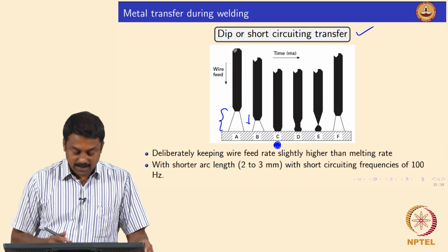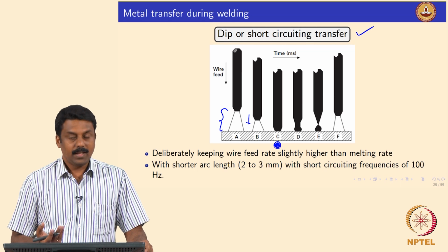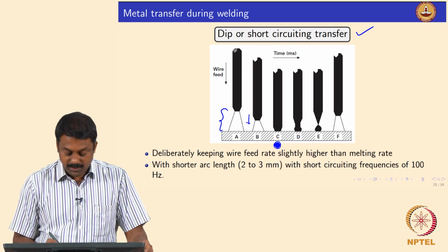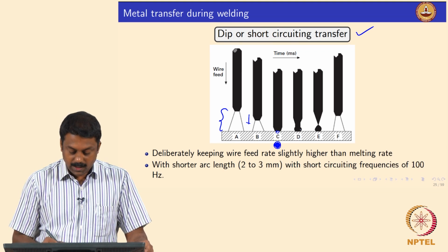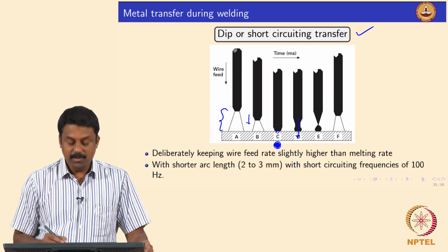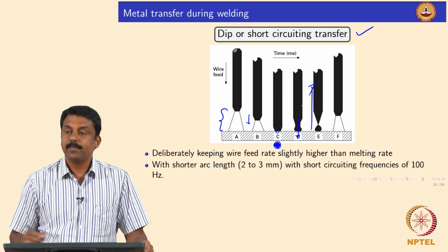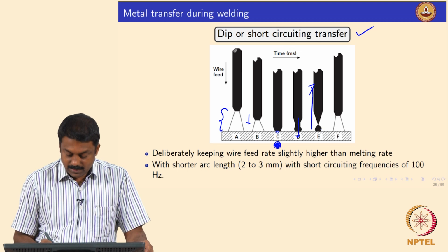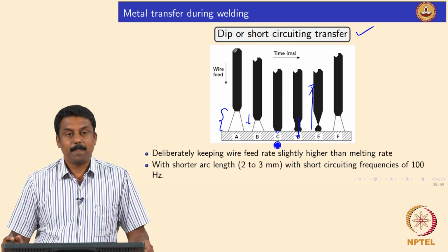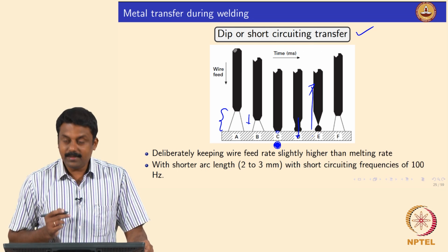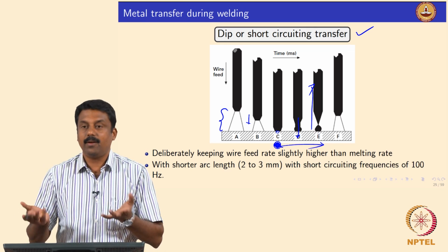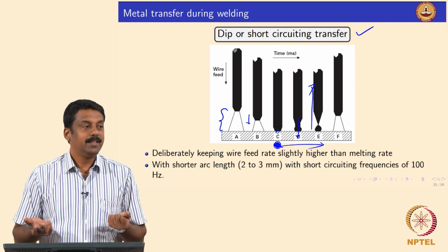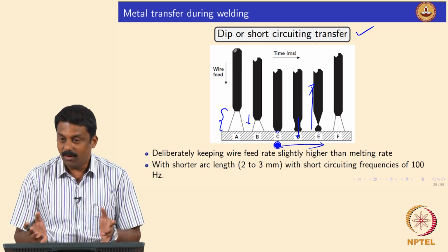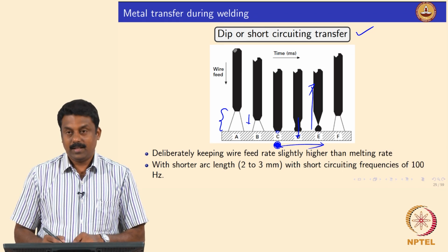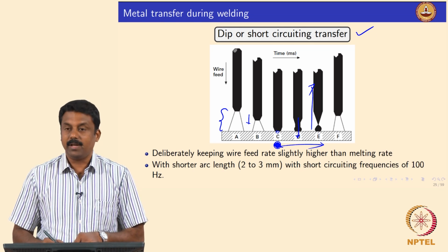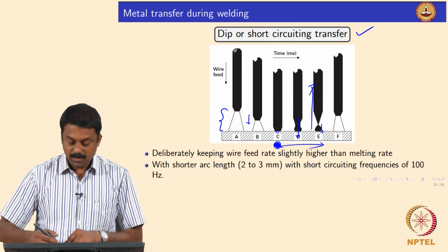is not it. And then what happens? So, once you have a short circuiting happens, you can also transfer the droplet to the workpiece. So, you form a droplet, and then once you are dipping it, you melt the droplet, and then subsequently you can pull the wire back. So, whatever is molten is detached by the surface tension of the weld pool. Yes, it is clear. And in this process, the advantage is here, during these 3 steps arc is not there, is not it. So, the moment the short circuiting happens, arc is gone, okay. And then you can dip the filler, okay. Either filler can melt before the short circuiting or during short circuiting it can melt, and then you can transfer the droplet by retracting the wire back.